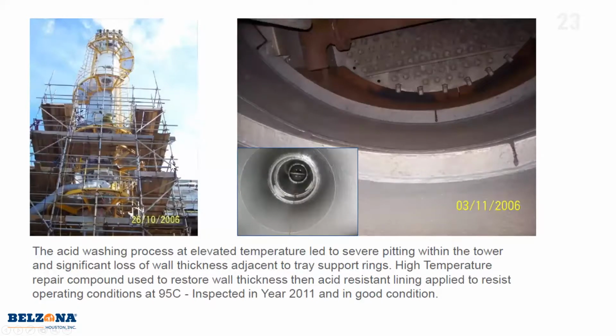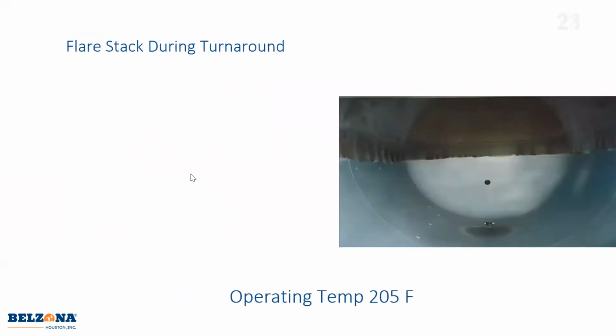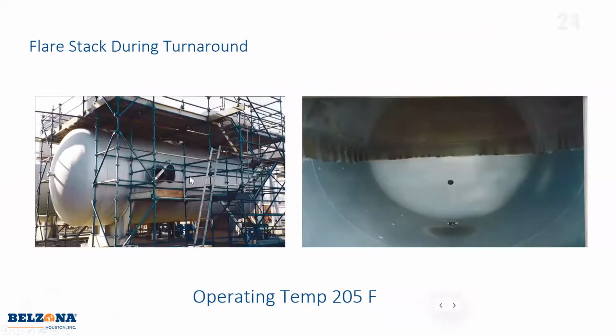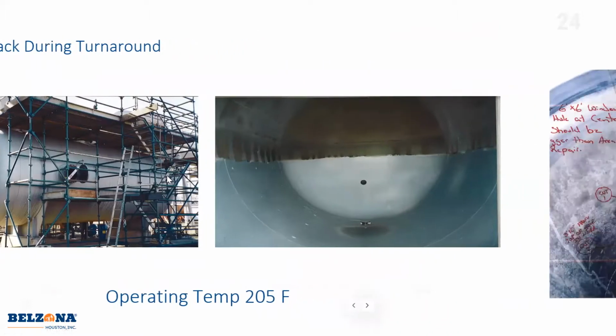We've also done jobs where it's not always coating every part of the vessel. For this one, a couple of trays were having issues underneath the trays. About a 10-foot section in height was suffering the most, so we coated that section. This one was just the bottom half having issues, so we coated the bottom half.